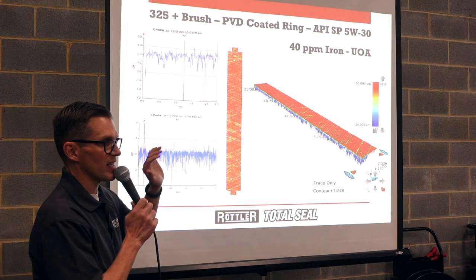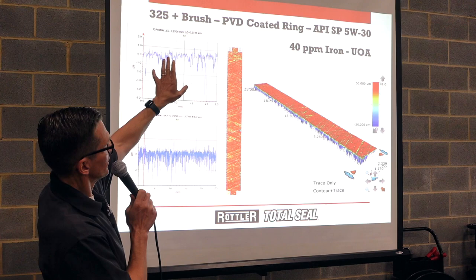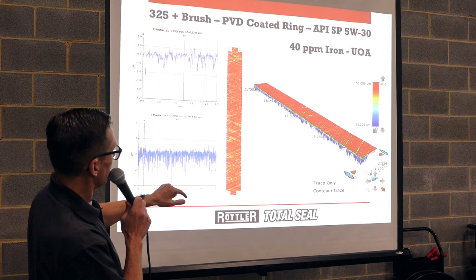Now we went in and brushed that same surface before we ran the test. So with the brushed, coated ring back in the regular oil, you can hardly tell where it stops. Right over here, you can see this is rougher than that, because that's right where the ring stops, about there.